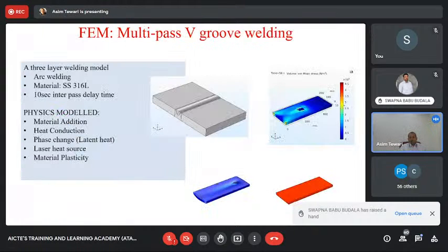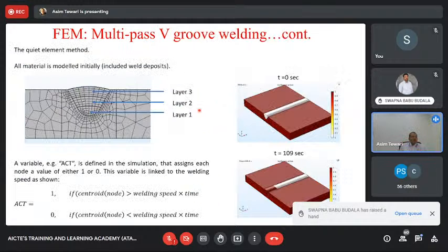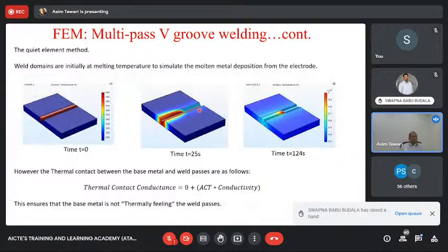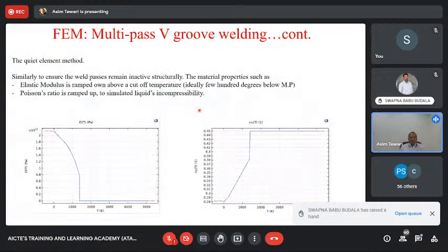So now we can perform this by various multi-passes, not just one pass. So we can add one pass, two pass, three pass. So we are adding multiple passes here, in this case, 3 passes. And in each pass, when you add and do that again, the temperature of the substrate is no more the same. The temperature has slightly heated up because your previous pass had heated the material up. And you can come up with very, very complex strategies of how this will happen.